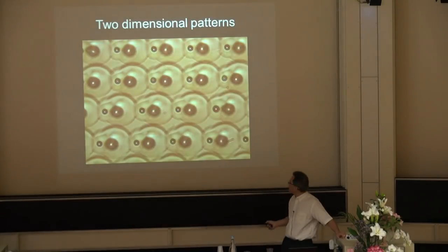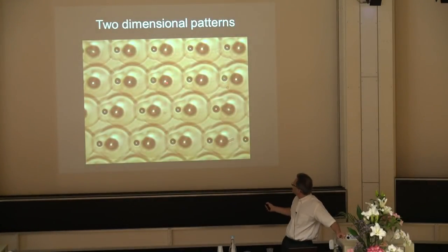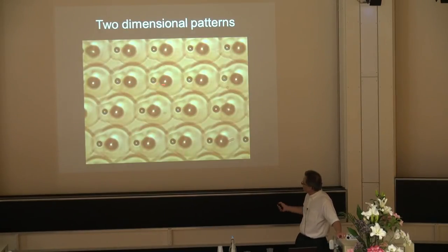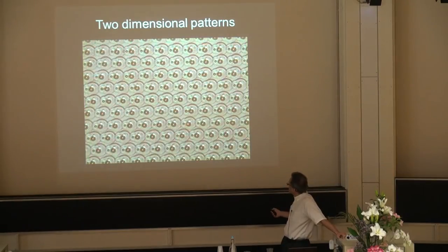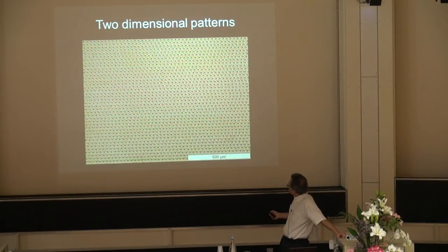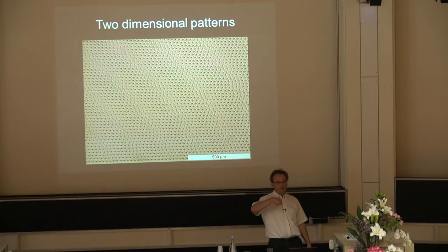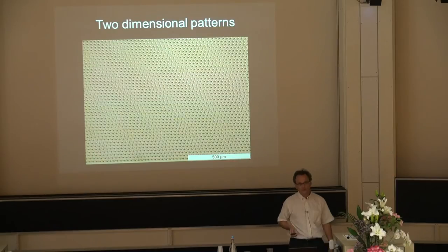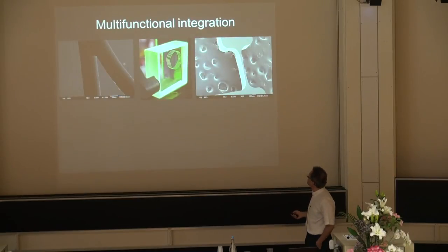It's fascinating because you see, for instance, this sort of bubble with a satellite one. Now this is looking at certain magnifications. Now I demagnify, I demagnify, I demagnify. You see, it's extremely irregular. Okay, and again, the laser was not stopped. It just kept on writing continuously. But this forms due to this oscillation system.